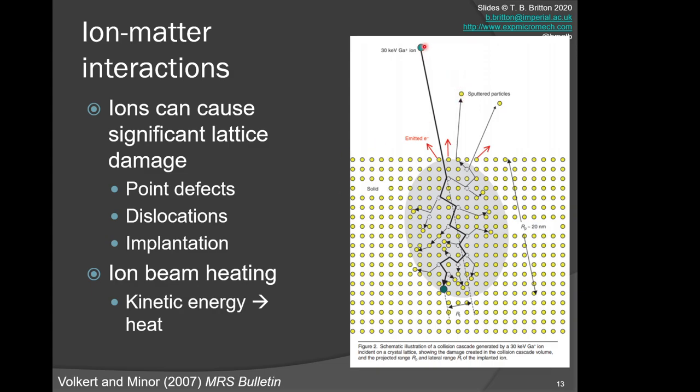We've now focused our probe on our sample. We should consider what happens as the probe instances in our crystal. Effectively, the ion will go into the material and scatter. As it scatters, it's a heavy ion and will knock primary ions of the lattice off their lattice sites. You can get those knocked off such that they can be liberated out of the material, and you can also get secondary ion knock-off, which is why you'll get a sputtering volume from one primary high-energy ion. You can get the emission of electrons from near the surface. You have a charged particle that can knock off electrons. You'll notice that as it goes into the material, it will knock into the primary atom and scatter multiple sites, creating a cascade of damage through the material. The knocked-off ions can also cause damage, and you'll get those secondary knock-on events.